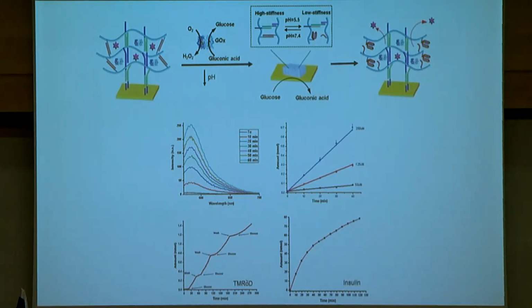So until now, we did everything manually. The electrochemistry didn't enter into our story. And we have now to go to the next step and to convert this entire change of the pH by means of electrochemistry. If you recall from the first slides that I introduced in my talk, we had the oxidation of glucose using a relay unit to make gluconic acid. So if we can make gluconic acid in the presence of a relay unit, we can induce at the electrode surface a decrease in the pH and open our hydrogel.